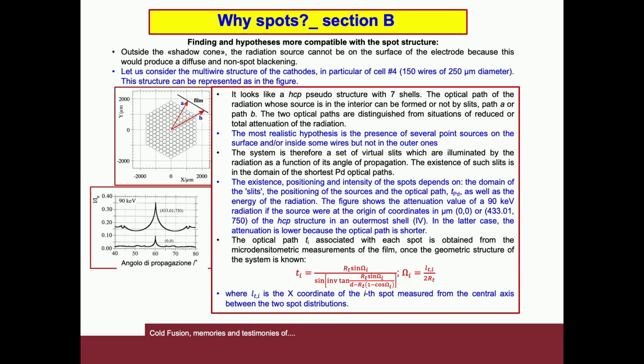The optical path associated with each spot is obtained from the microdensitometry measurement of the film, knowing the geometry structure of the system. Here, the calculation is represented by this equation written in red, where L_φi is the x-coordinate of the ith spot measured from the central axis between the two spot distributions.